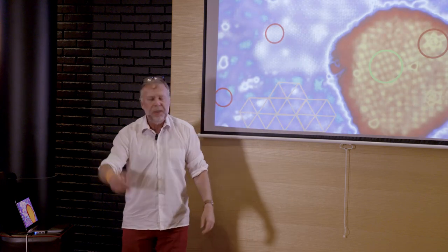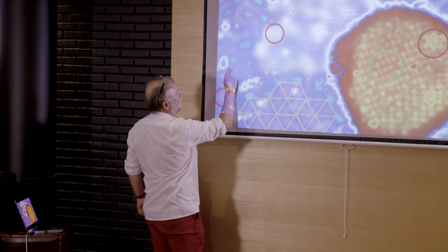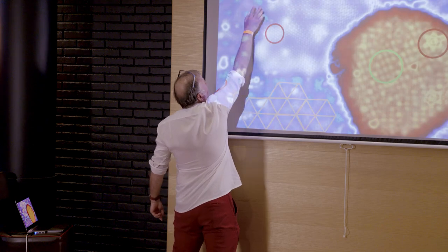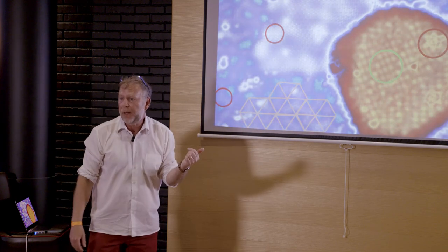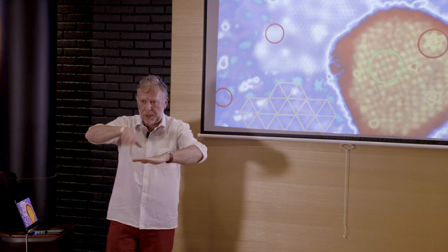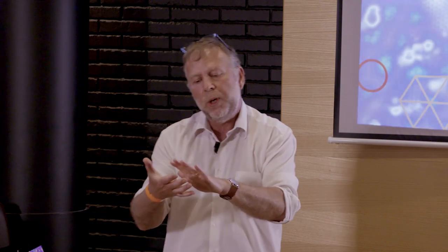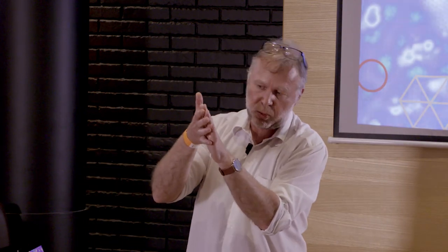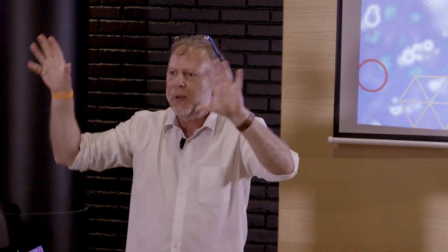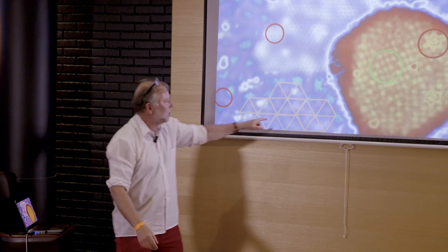So silicon carbide is below because, you see, there is something which seems to be periodic. You see the light blue? It seems to be rather periodic. In fact, it is a moiré. Graphene has a periodicity on silicon carbide, which has another periodicity. And when you put two tissues with two different periodicities together, you can see some things which are called moiré, which are very nice. And there is a periodicity inside. This is exactly what we have here.